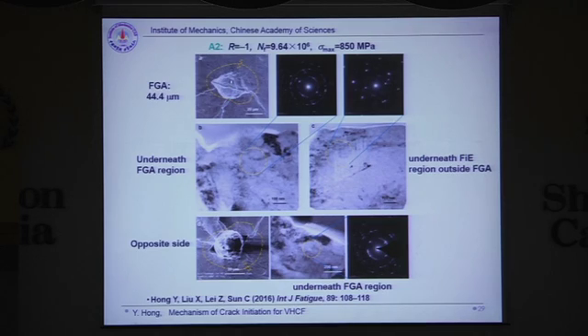And okay, for this negative and this positive fracture surface, we see that in the FGA location there are discontinuous circles, and we cut the FIB sample across the boundary of the fisheye and FGA. So a part of the FIB sample is the FGA region, and another part is the fisheye outside FGA. And this shows that the part outside FGA is almost isolated spots. So only the region of FGA is a kind of fine microstructure. And in the area of FGA, it is discontinuous circles.